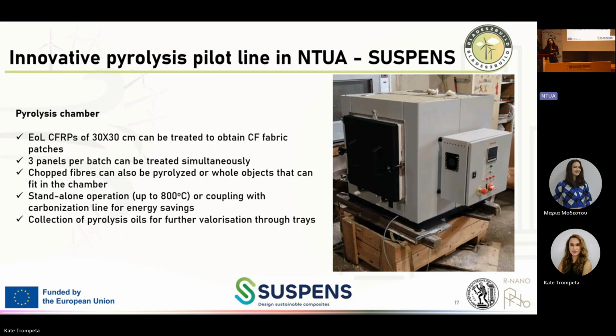But our research was actually focused on recovering full length in full parts and not shredding down the material. This was done for the purposes of BLADES2BUILD, but in general, we're trying to recover the whole fabric or the full length if we are talking about unidirectional composites. But our limitation right now is the 30 by 30 chamber. So it mainly depends on the size of the reactor, and also on the way that the composite has been produced.